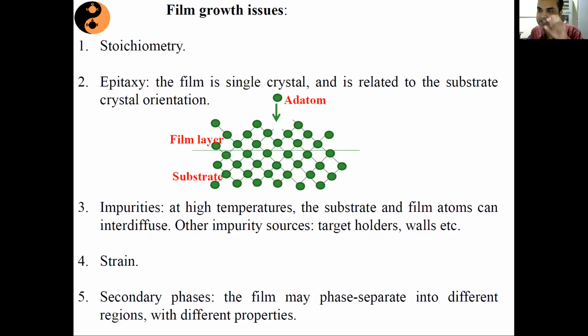Remember, epitaxy is not the property of the film. It's a relation between the substrate and the film. When the film retains a similar crystalline arrangement as that of the substrate, we call that the film is grown epitaxially on that substrate. Another issue is that of the impurity. What is impurity? When you are growing films at high temperature. Why do we need high temperature to grow films? Because as I said, the evaporants which are falling on your substrate first try to attain a thermal equilibrium.